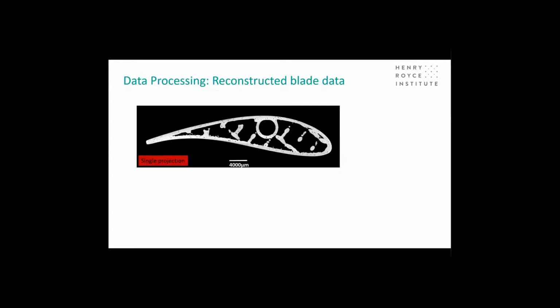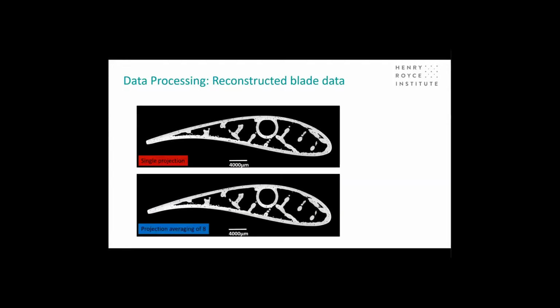So if we want to measure defects, an important question to ask, and here's an additively manufactured component, is what resolution do we need, and what setup do we need so that we can measure the defects that are most of interest. Now, of course, if you're measuring a part and you want to understand its fatigue life, then you can identify using fracture mechanics what the critical defects are likely to be, and that will enable you to set up the parameters of the scan such that, whilst you may miss some of the smaller pores, you will capture those which are likely to be critical defects and to limit the behavior of the material.